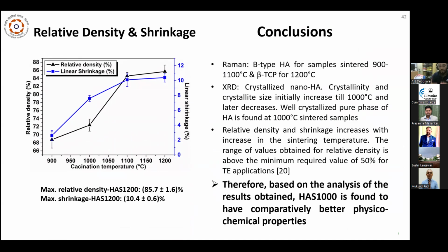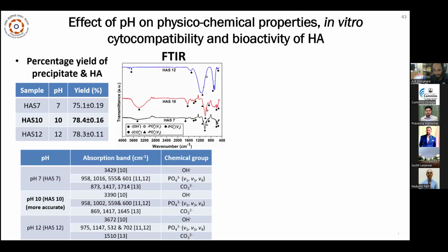From the above analysis, it can be concluded that B type hydroxyapatite is prepared at a temperature range of 900 to 1100 degrees Celsius. Beyond that, there is formation of beta tricalcium phosphate. From the XRD analysis, crystalline nanohydroxyapatite is prepared. Based upon the analysis, it can be observed that at a sintering temperature of 1000 degrees, it is found to have comparatively better physicochemical properties, and it is used for the next characterization analysis.